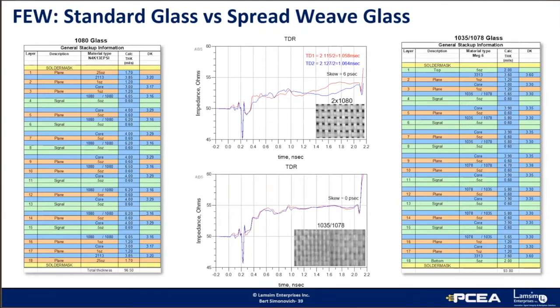As a rule of thumb, though, we budget about 20% of the baud rate for skew. So for 28 gigabaud, that's roughly 7 picoseconds. And as you can see, we have almost reached that budget with the 1080 glass.